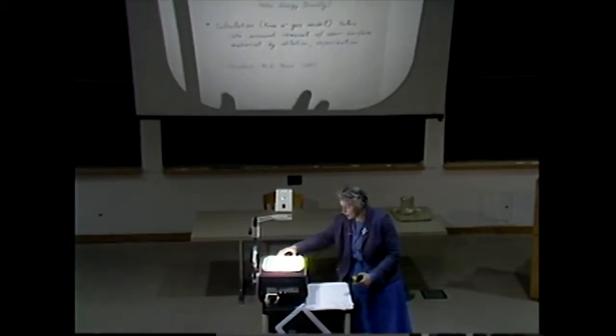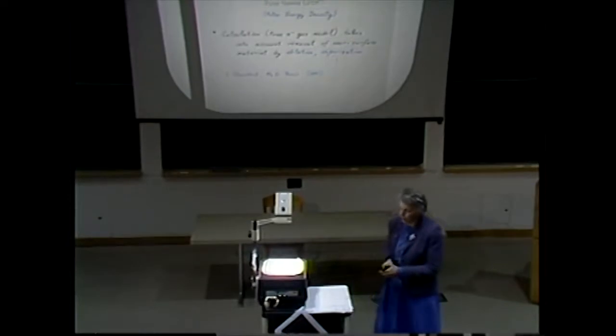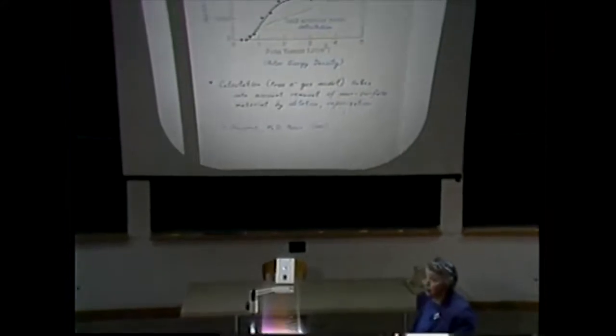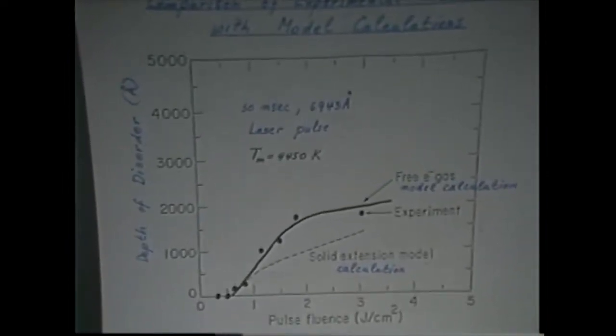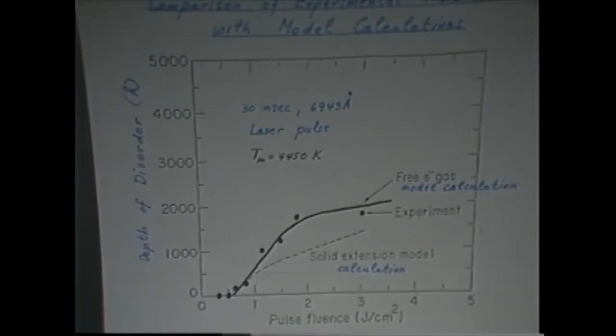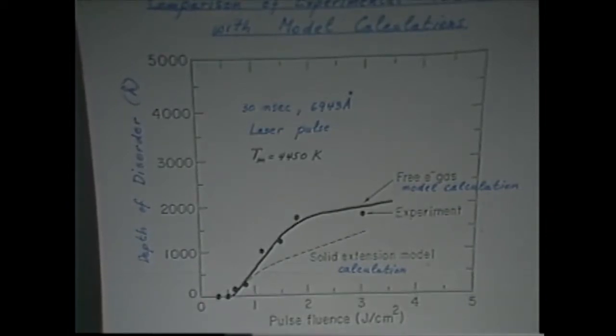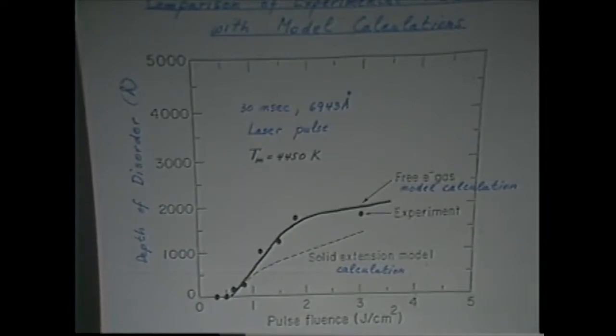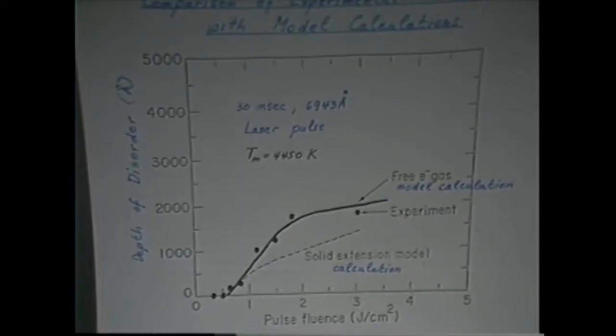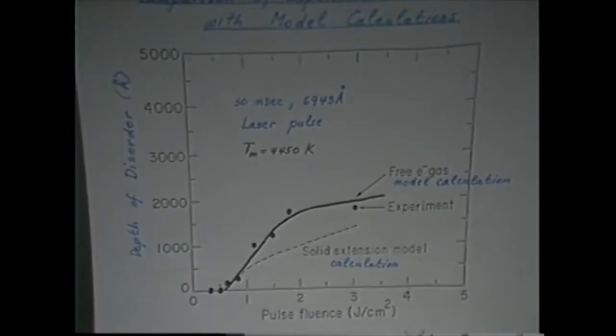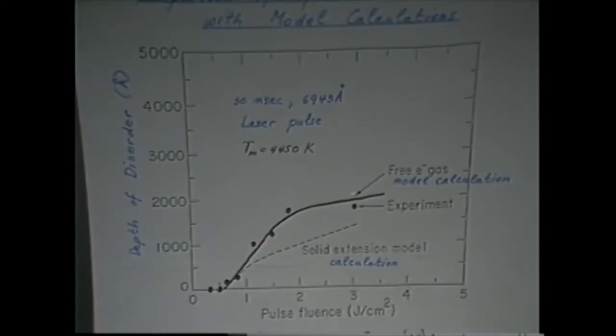Now, to explain the depth of disorder quantitatively as a function of the amount of laser energy put into the system, John Steinbeck has formed a model. He solved the diffusion equation, the heat equation, with a driving term having to do with the laser energy that's put in. And you have to take a lot of effects into account. It's not only melting, but it's also vaporization of the surface, because the vaporization point of carbon is very close to the melting point. And when all of this is done, we took two limits into consideration.